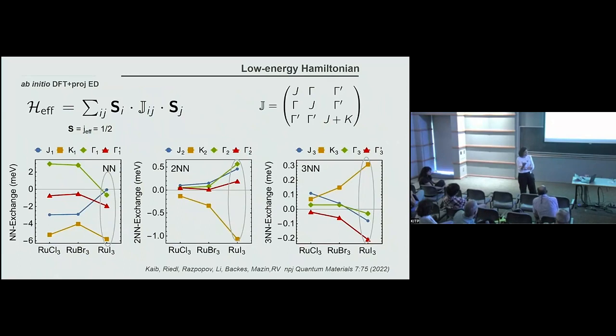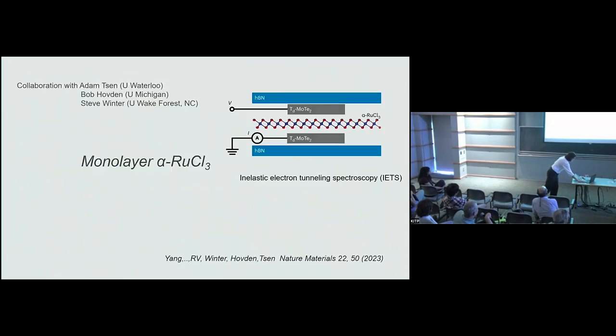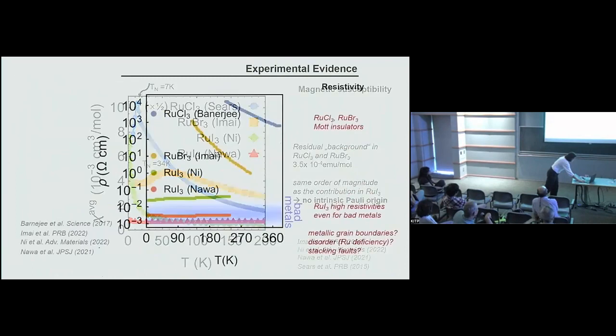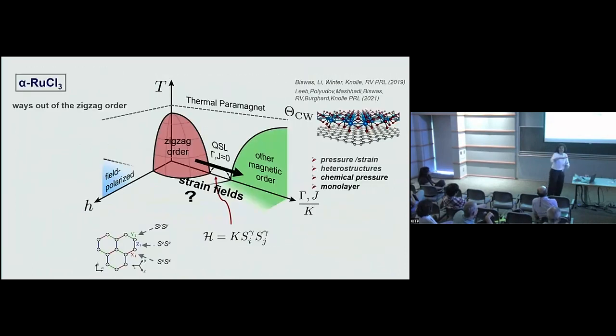Yes. The problem is you start to introduce disorder. So I think the most promising way, to be honest, is these heterostructures, because depending on the substrate, you don't want to blow up the lattice in all directions exactly the same. In this type of heterostructure, what we find is that the strain is anisotropic because there is an important lattice mismatch, but it is enough to give this negative pressure. And this is a clean way.